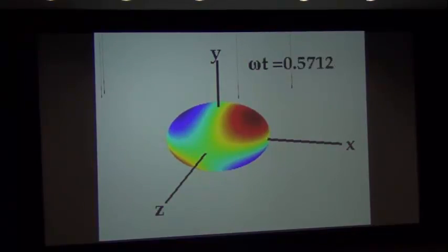Now I want to, see that? I mean, I'm rotating, I'm doing an experiment now. You see omega t is going from 0 to 2 pi, but the shape is hardly departing from a liquid at rest. Isn't that interesting? I can explain the eta prime and the eta double prime behaviors with orientation, even though there is hardly any reorientation. These molecules are just jiggling gently about the equilibrium state.